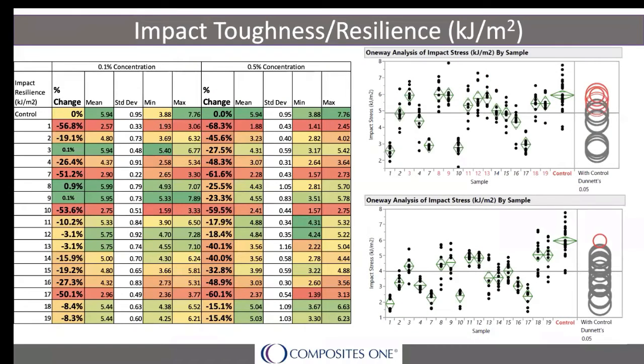So if we look at just the toughness results for both loading levels, you can see again that the 0.5% loading shows a lot of red and orange in the percent change. None of that is good. But in the 0.1% loading, you'll see a number of green results that are good, with sample 9 being one of them, and sample 18 being yellow at an 8% change. But that 8% change is not statistically significant for us to know that it definitely has an impact.